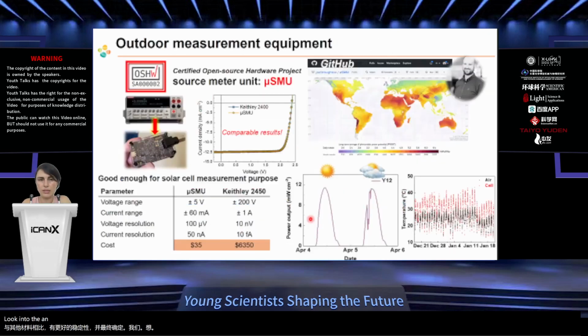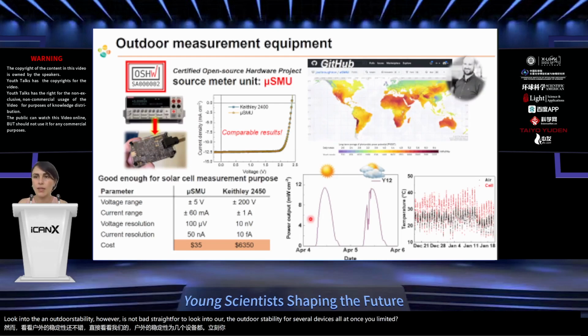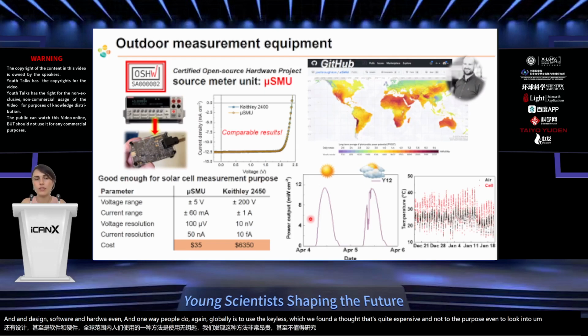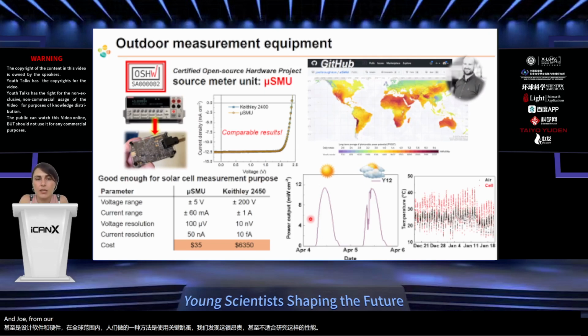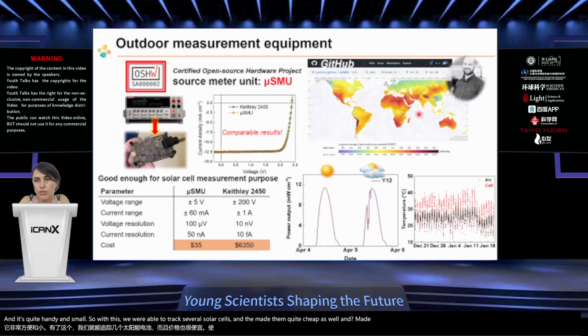To finalize that, we wanted to look into the outdoor stability. However, it's not that straightforward to look into outdoor stability for several devices all at once. You're limited by your equipment and design, software and hardware even. One way people do this, again globally, is to use Keithleys, which we found quite expensive and not suited to the purpose. Joel from our group has designed this micro SMU that is quite enough for JV curves, which we also think is suitable even for bio applications, and it's quite handy and small. With this, we were able to track several solar cells and made them quite cheap as well, and made it open source, but we're happy to help you out with the design of these micro SMUs.